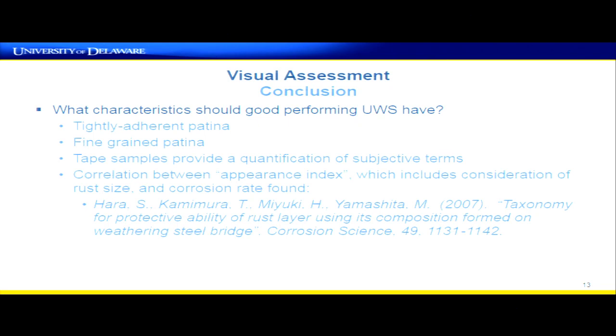So some concluding comments about visual assessment. It's highly dependent on what good performing uncoated weathering steel should look like. And the qualitative statement is it should have a tightly adherent patina and it should have a fine-grained patina. So those are subjective terms. So the tape sample gives us a quantitative way to apply some consistency to exactly what that means in the inspection process. It's also worth noting there's been some work done in Japan where they have also looked at these particle sizes and correlated that to corrosion rates. So there's a real opportunity there, I think, to make this a more engineered process.